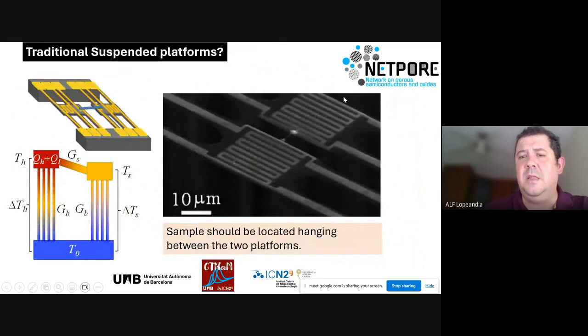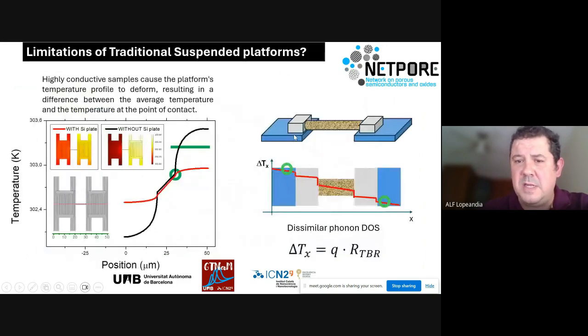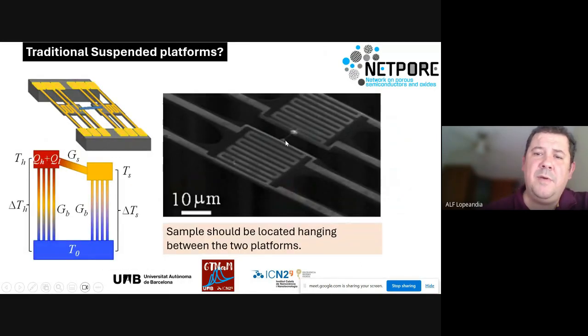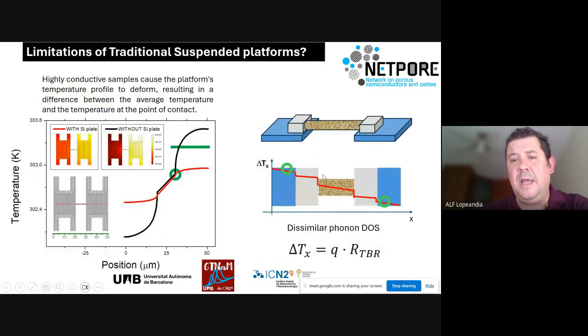It essentially means that in these nanowires, most of the temperature drop was across the nanowire. It essentially means that this effect is minimal in this material. But what happens if we have a highly conductive material? It may happen that the temperature drop due to the TBR, due to the thermal contact, could be higher than the temperature drop within the material. Then the uncertainty, and this project was initially thought of as a metrological project, this uncertainty is a dominant one in highly conductive materials.